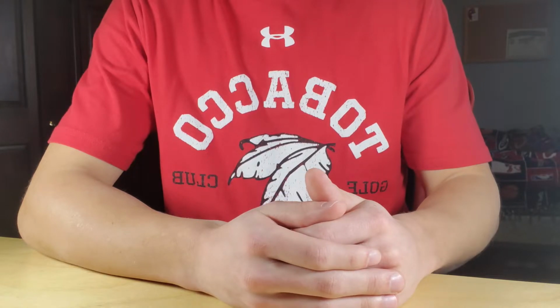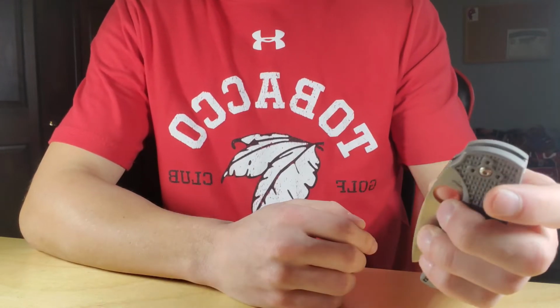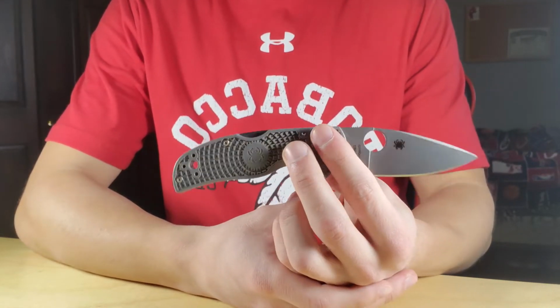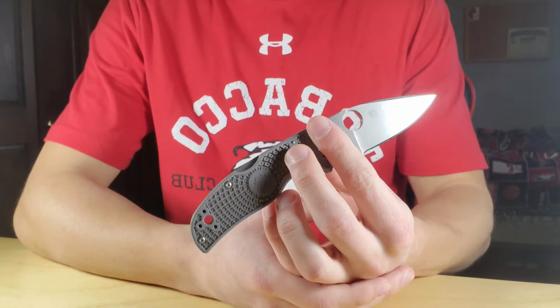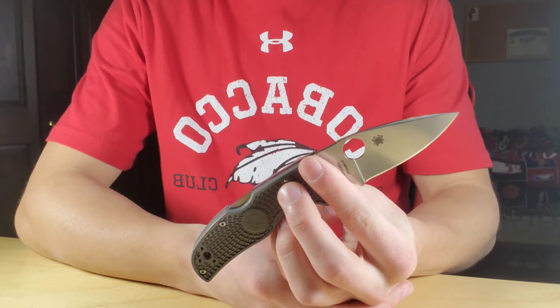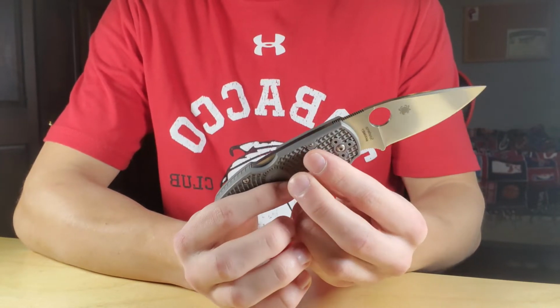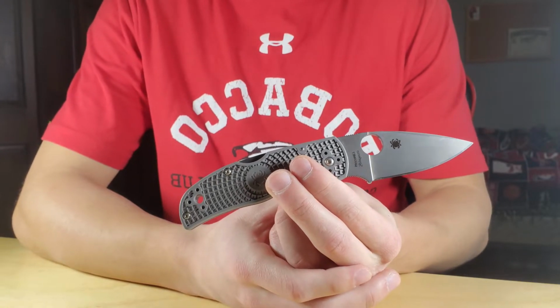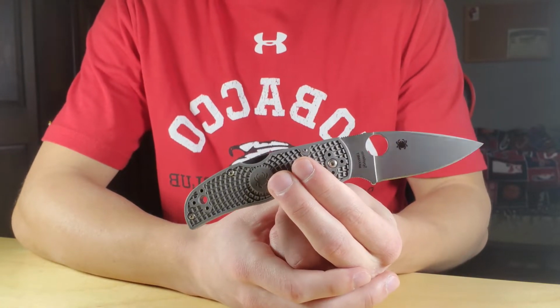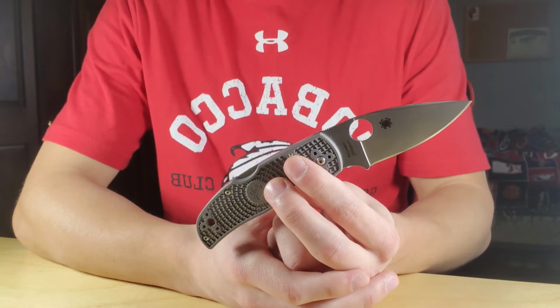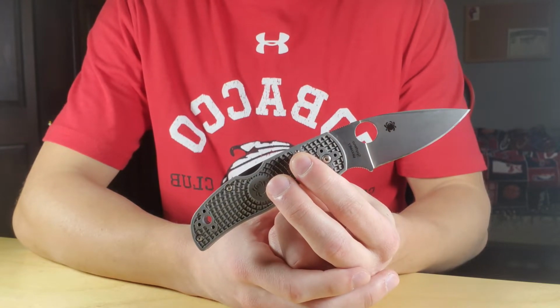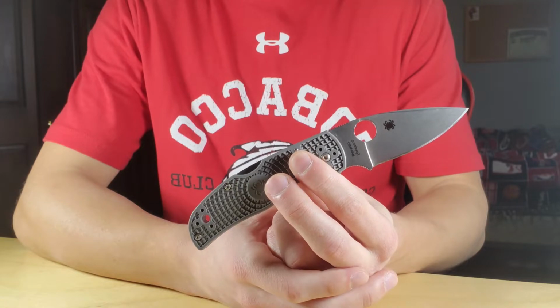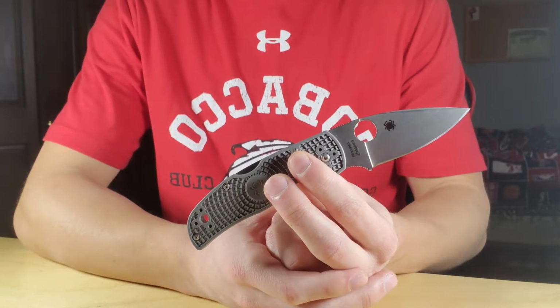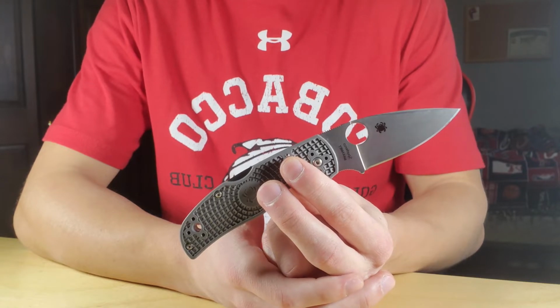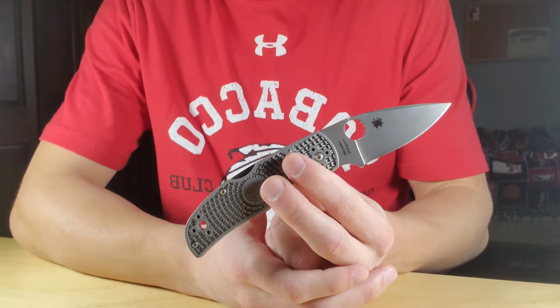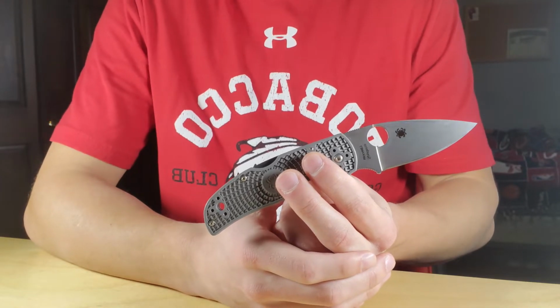The types of carbides and the sheer volume of them is what drives edge retention from a composition standpoint. So like Maxamet has a ton of carbides and a ton of high hardness carbides, as well as the steel matrix being able to get hard because of its composition, which is what leads to its high edge retention. Compare that to something like S30V that only has really vanadium carbides, and because of its composition can only be run to like 61, 62, somewhere in that range. It's just not going to cut as long because the steel composition just isn't there, the steel type.